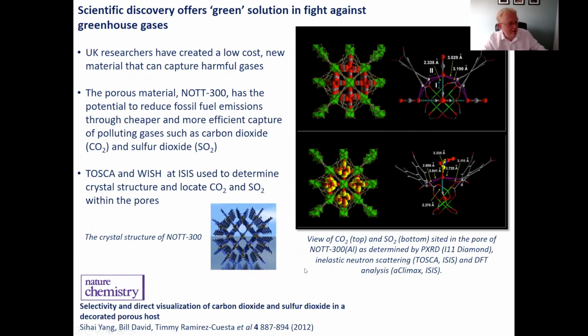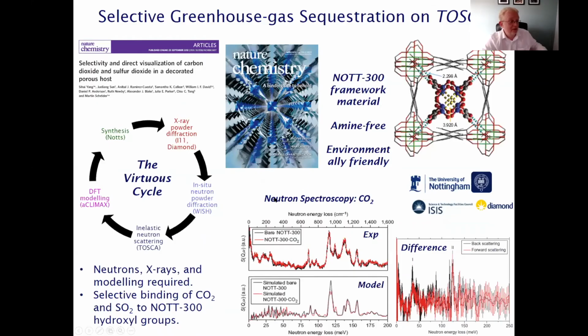This is some work that Nottingham University did looking at their NOTT-300 MOF material, which is the world's best MOF for capturing SO2 and CO2. And they did some inelastic spectra looking at the motion of the SO2 and CO2 molecules within the cages of this MOF material.